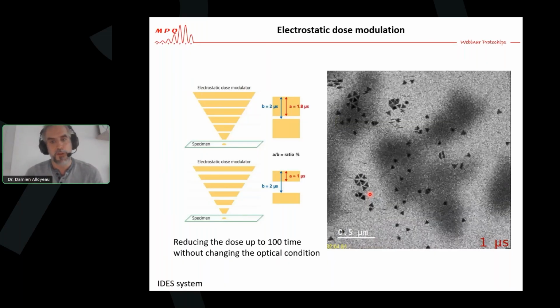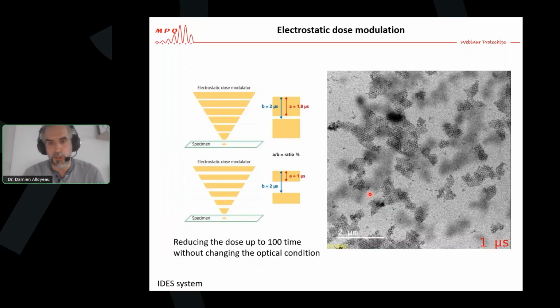And we had a lot of trouble being able to study the structure of those supercrystals, because we needed a high enough magnification to observe the structure, but when you increase the magnification, you increase the dose rate and you degrade the nanostructures. So what we did, we used an electrostatic dose modulator, the IDES system, that you can have on a JEOL microscope. And the idea of this electrostatic dose modulation is to block.